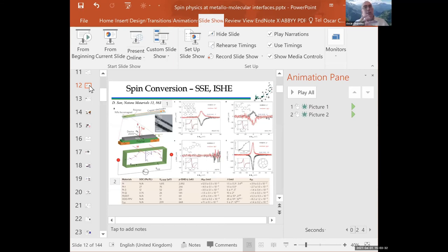So you are asking how the curvature enhances the spin orbit coupling? Yes. Because you are deforming the orbitals. Rather than having them flat, in plane, now you have your pi bonds and antibonds that have to be pushed out of plane. So you increase the coupling between the spin and the orbital that now is not in plane. It's not all flat in the same position. So in theory, the more you force your orbitals to be out of their, I wouldn't say natural position, but their all collinear position, the higher your spin orbit coupling becomes. And you can do simulations to predict this.